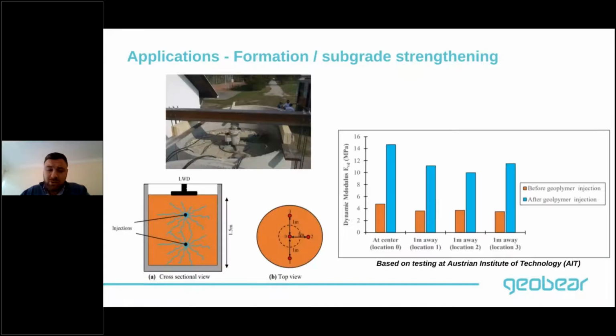We've done some testing in Austria where we had a testing pit, and we filled that testing pit with some really soft soils. And what we did, we basically measured the modulus of the soil using the LWD. I'm sure some of you are familiar with this machine. We measured the modulus of that soil before the injections, and then we measured the soil modulus after the injections. So before the injections, the soil modulus was around 4 MPa, so very soft stuff. If you've got that under the railways, the design will be a challenge, I can assure you of that.